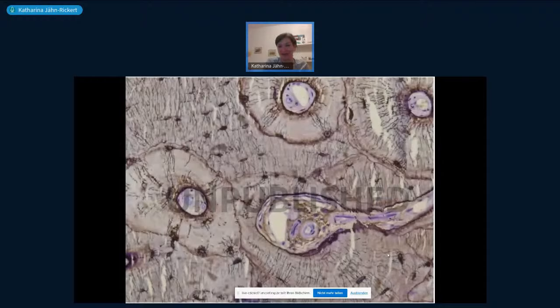There's also a wonderful staining that Tamara Alliston has reintroduced into the bone world, the Ploton silver precipitation, and what you see here are again the osteocyte lacunae, where the silver has precipitated on the lacuna surface, and you can also appreciate the canaliculi and the connections here in this human cortical bone specimen. And there you can really get an impression of how the connectivity is. So how many canaliculi are there? Maybe, as you can see here, these areas are not as connected as the ones here. So that's quite a nice staining, and there are good opportunities also to count canalicular connections.